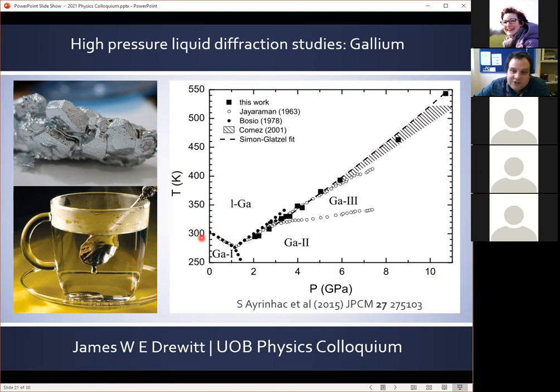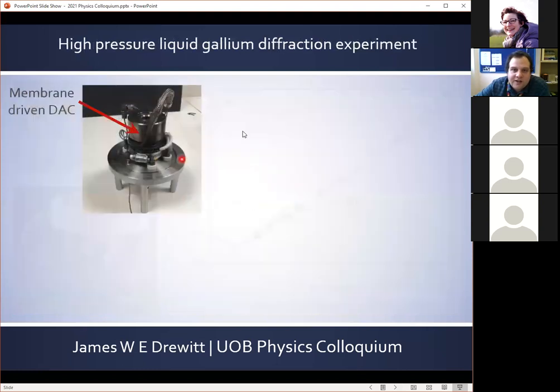And actually this is interesting because at room temperature, all you have to do to melt gallium in a pressure cell is to squeeze it. And so with increasing pressure, the melting curve goes down until around 1.2 gigapascals when it starts to increase again. And the structure of the high pressure gallium liquid previously wasn't much known, and so that's why we decided to look at it.